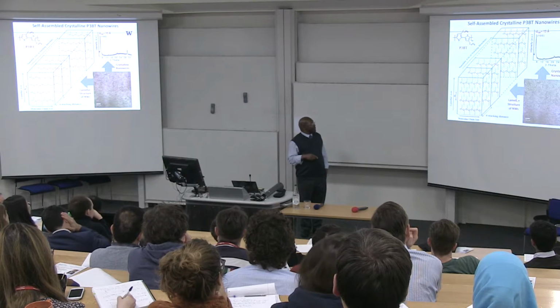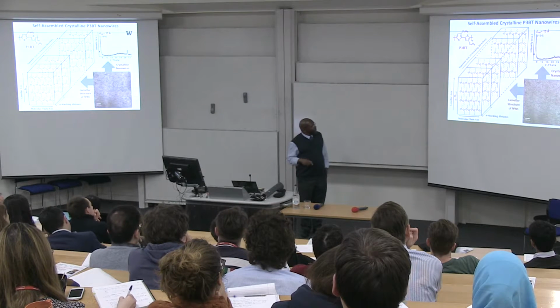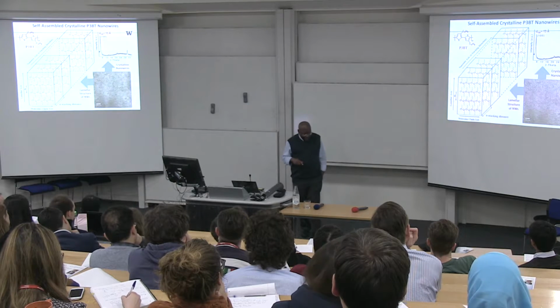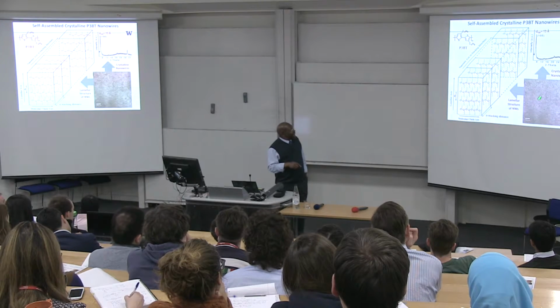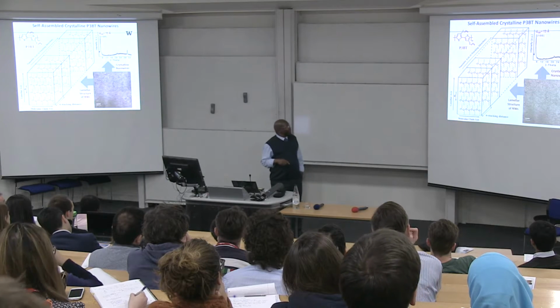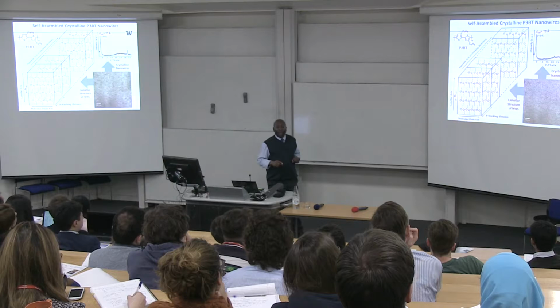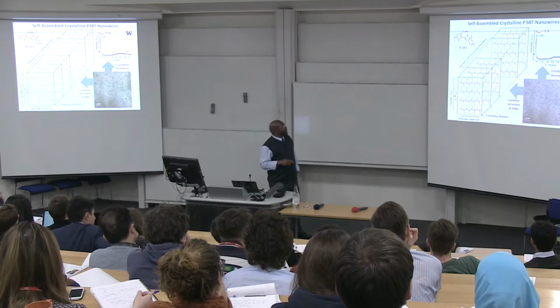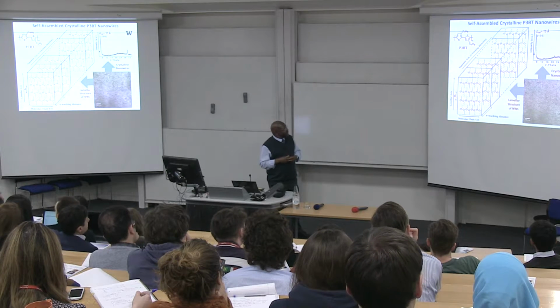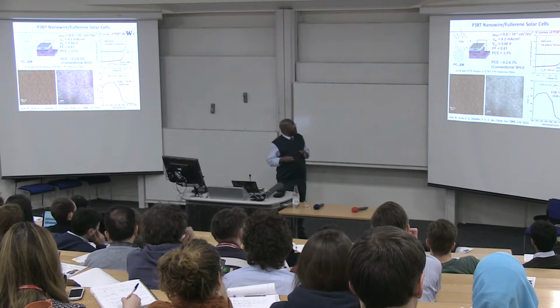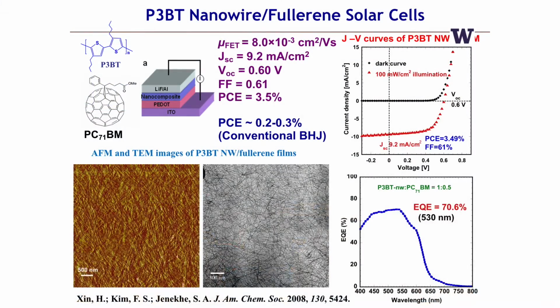So, for example, such nanowires for this particular polythiophene are shown here. The wires are on the order of 10 to 15 nanometers, so ideal within the exciton diffusion length scale, and quite crystalline, so presumably it should be able to transport charge very efficiently. All right, so here, by mixing the fullerenes with the polymer nanowires, we demonstrated that we can make devices